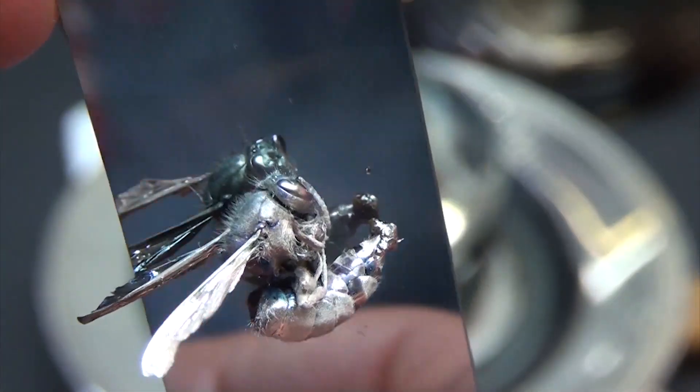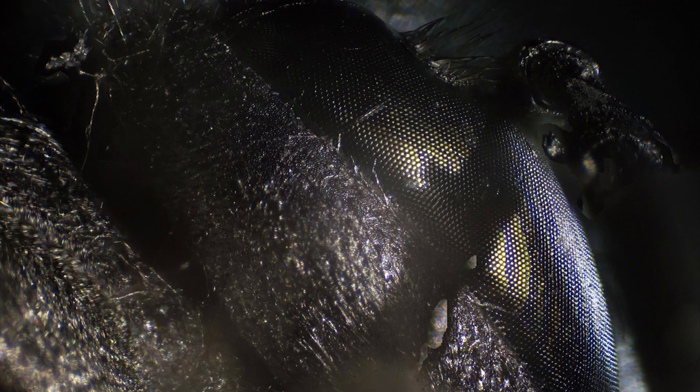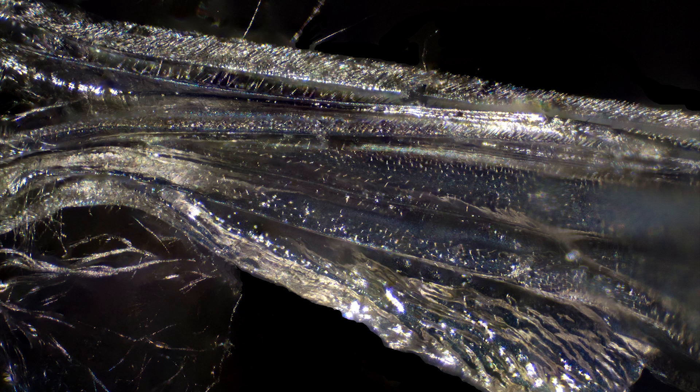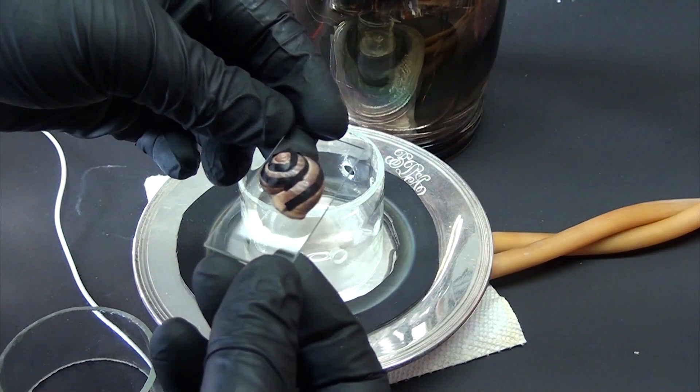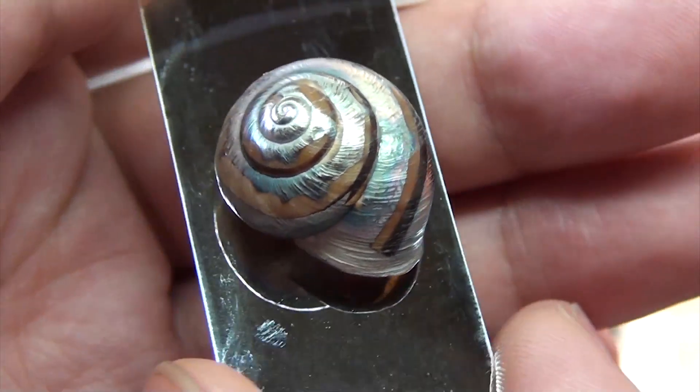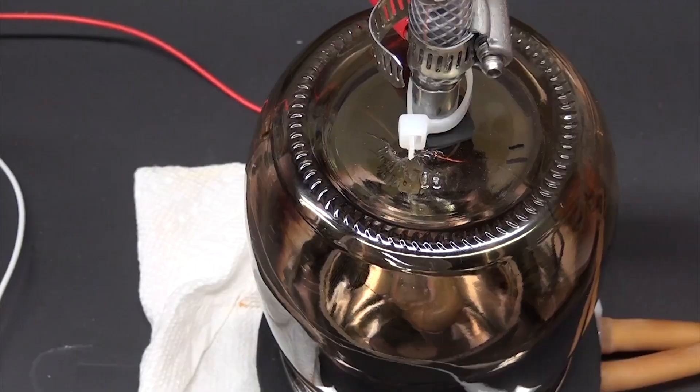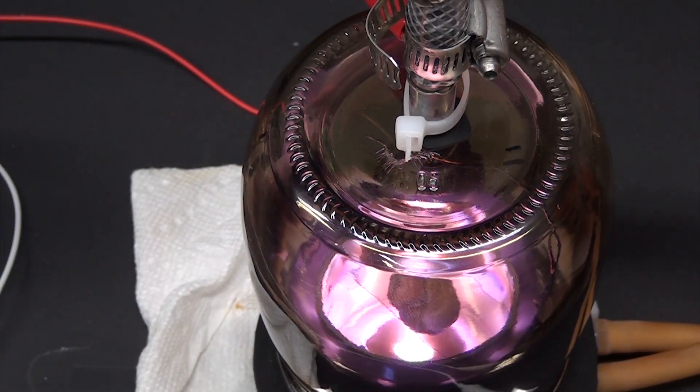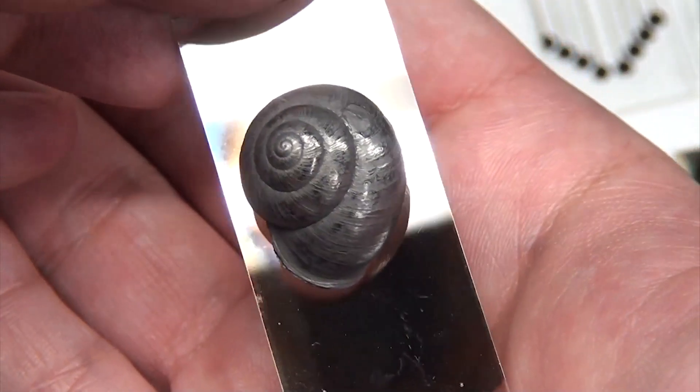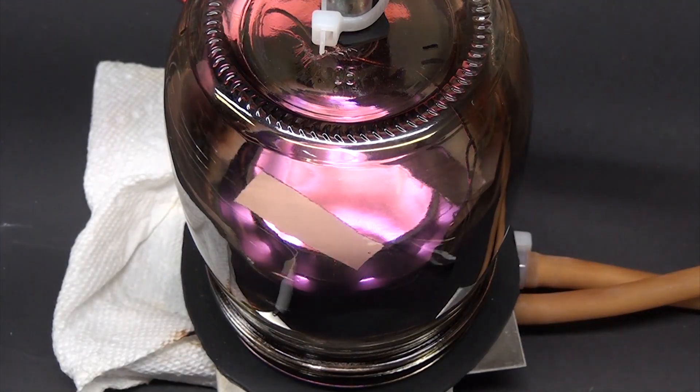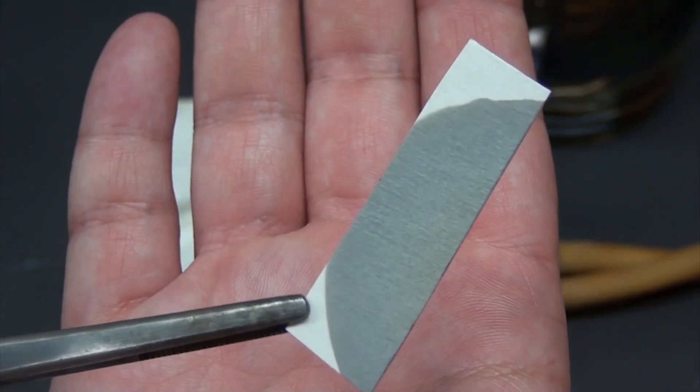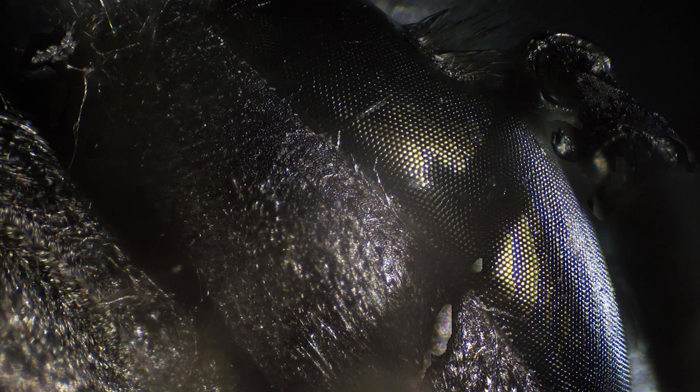I wanted to really see the detail up close, so I took a few pictures of it under the microscope and focus stacked them to make these awesome images. This really emphasizes that every little nook and cranny and even the smallest hair and detail is covered in metal. Just for fun, I also did a snail shell with a bit of vinyl mask, and it came out as this partly metalized shell with some of the original pattern still visible. I ended up doing another one later without the mask and using nickel metal, and it was a noticeably grayer metallic coating. While I was at it, I also tried some cardboard, and there wasn't so much as a scorch mark. It took the coating and had a gray matte finish from the very thin coat. Point is, biological samples and objects with weird shapes or are otherwise flammable or delicate can all be fairly easily covered so long as you're careful.